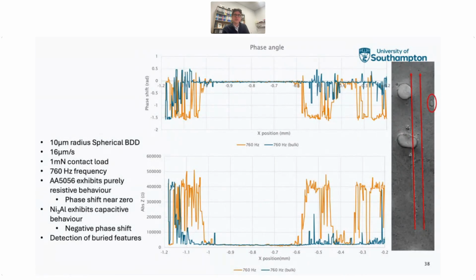What's quite interesting, we also found, is that you notice on the left part of the graph here, we're also getting a response, but necessarily in the absence of any apparent particle here. But what I have highlighted just up on the top right-hand corner is this little particle just poking through here. And it's useful to remember that microstructures are in 3 dimensions, and so potentially we think that there may be a particle perhaps just hiding under the surface here at the bottom, and we're picking up those interfacial regions there. So it could be possible that we might be able to delineate stuff that's potentially subsurface as well as what we can see from the planar section that we have here. But again, that's something we're currently trying to elaborate on to see if we can actually detect buried features.